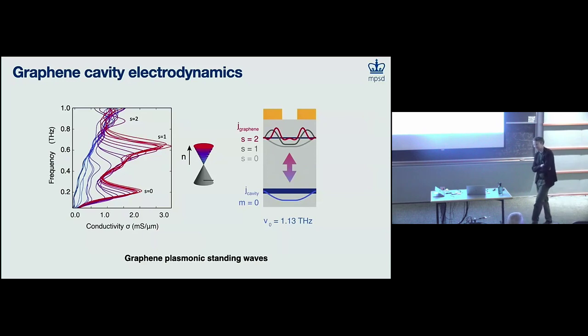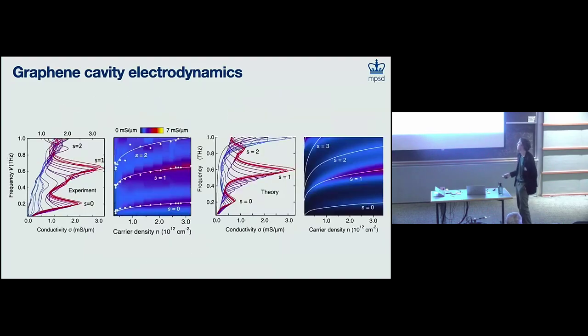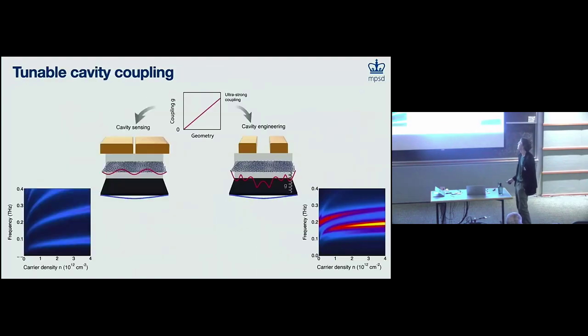Can I ask a question about the perspective, because I'm not sure I understand it correctly. When you say you want to go with narrower waveguides, in a sense you would reduce the capacitive coupling to the sample, but that would essentially make the sample invisible. Do I not understand? No. To be clear, we haven't measured this geometry. It took us a long time to figure out how to build a 50 nanometer gap, which we can now do. We have a device that's going to be measured, maybe even being measured right now. We've done a lot of simulations, the same simulations that accurately predict everything that we measure, showing that when you reduce that gap to 50 nanometers, it still works. You lose a factor, you gain a factor, but it all balances out, and we actually pick up a factor of 2 or 3 in signal to noise, according to the finite element simulations. But if you ask me in 3 weeks, I can tell you what our real measurements show on a real device.